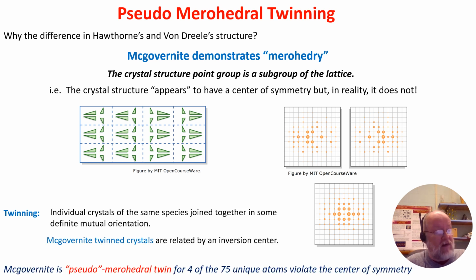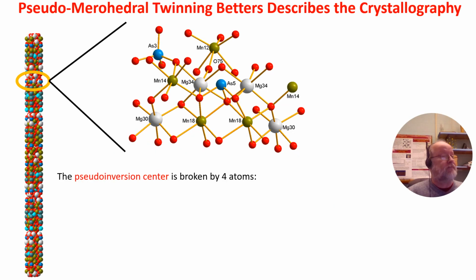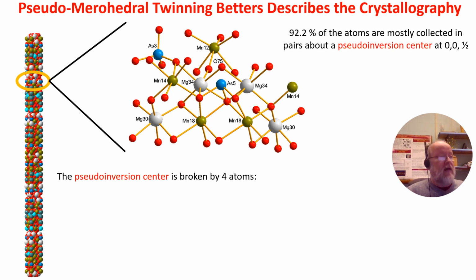Why is it the pseudo-merohedral twin? Because of our 75 unique atoms, 4 of them violate the center of symmetry. 4 of them do not have inverse equivalence. The other 71 do. Now, our model then, I think, reveals a better crystal structure because we don't need disorder to describe what we're seeing. The pseudo-symmetry is broken by 4 atoms.